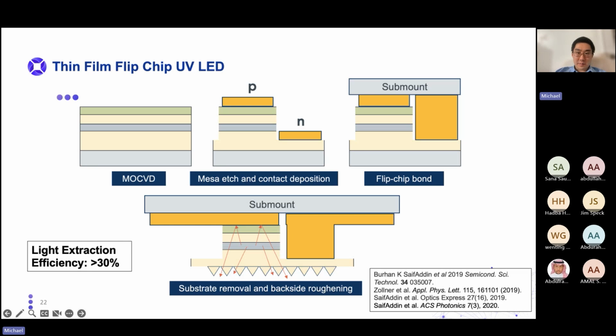So the process involves first etching down to the n-type, putting contacts on both of them, depositing metal, attaching a submount through flip chip bonding. So this is indium gold bonding. So gold, indium gold, and then mechanical pressure and heat, and that bonds the materials. And you can flip this over and then dry etch off the silicon carbide substrate and roughen the backside of the aluminum nitride. And this results in a light extraction efficiency of greater than 30%, which is actually greater than what we have now with the sapphire world record epi.